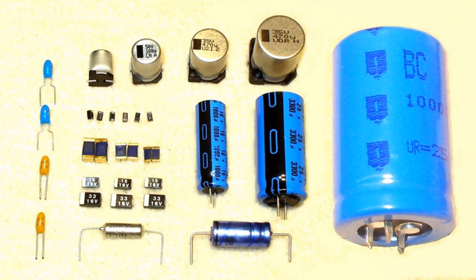They ground tantalum to a powder, which they pressed into a cylindrical form and then sintered at higher temperature between 1500 and 2000 degrees Celsius under vacuum conditions to produce a pellet slug. These first sintered tantalum capacitors used a non-solid electrolyte, which does not fit the concept of solid electronics.